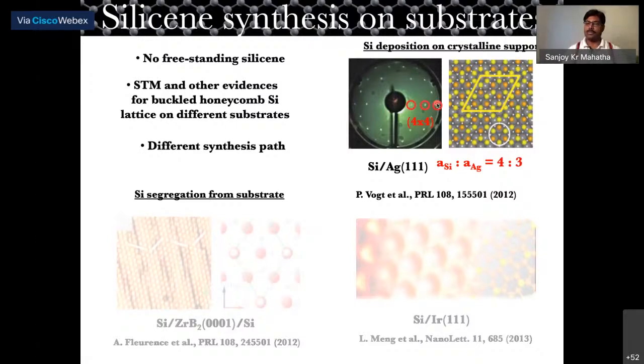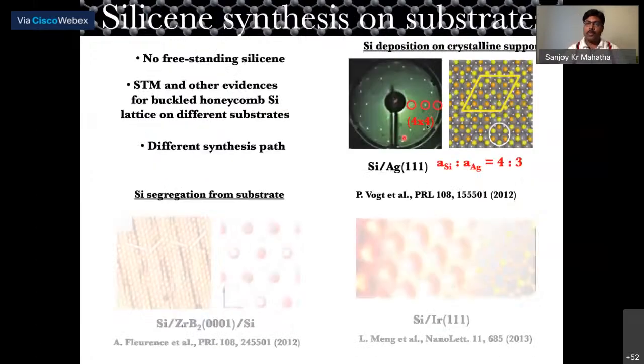Okay. In this paper, a PRL from 2012, this group claimed that they could achieve this single phase silicene with the silicene 4 by 4 structure. But then we studied the same system using the same kind of growth recipes, and what we found is that this is probably not true.